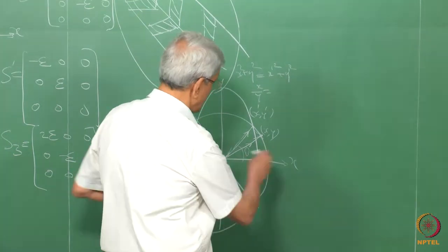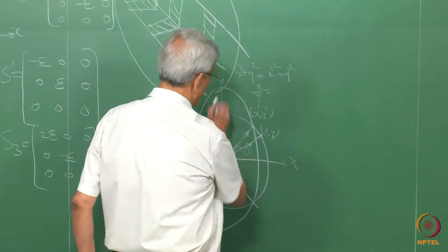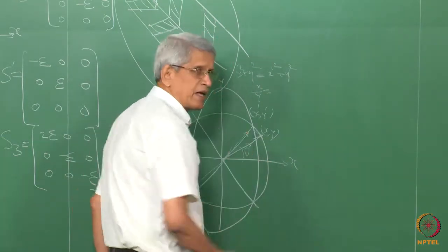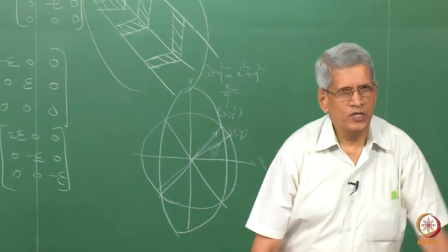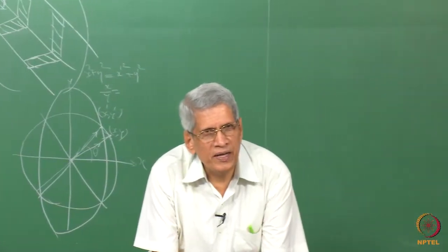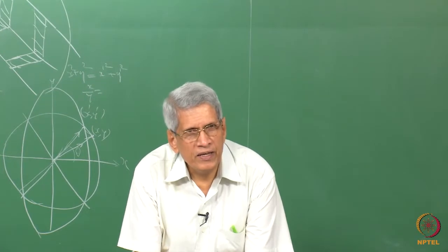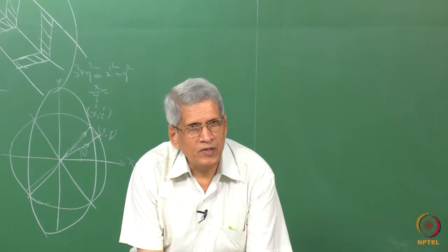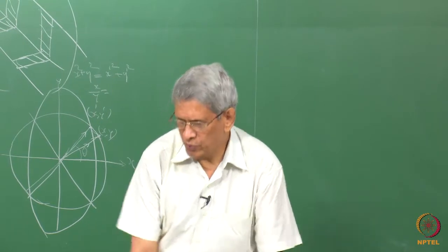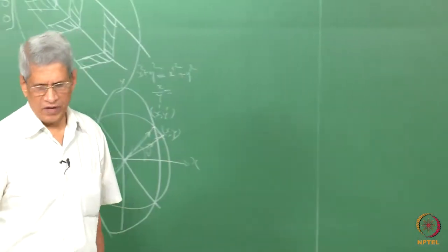So now, since we know these specific directions, we can find what is the direction which is going to be that particular one, and the plane which contains that direction. Okay. Then we can identify the plane using stereographic projection. That is how these habit planes are identified.